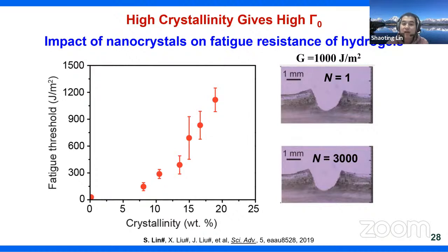When we apply a very low stretch, the crack does not propagate. As you gradually increase the stretch, the crack propagates at a certain point, and eventually you can measure the crack extension rate. Each stretch corresponds to a so-called energy release rate. But to calculate the energy release rate, we need another test. We need another sample with no notch.